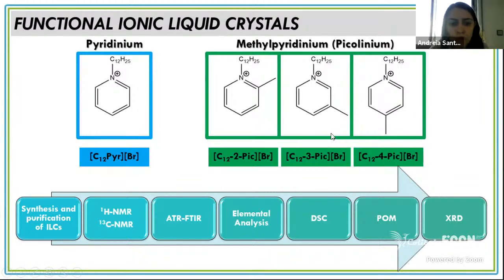All prepared compounds were characterized first by NMR, FTIR, and elemental analysis in order to confirm the chemical structure, and then by DSC, POM, and X-ray diffraction in order to study the liquid crystalline behavior.